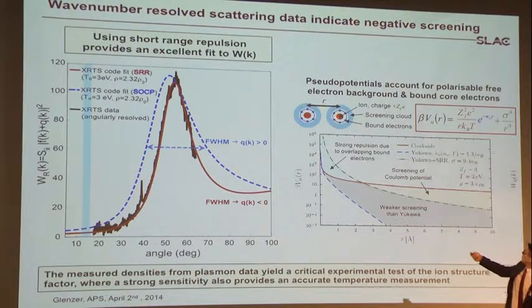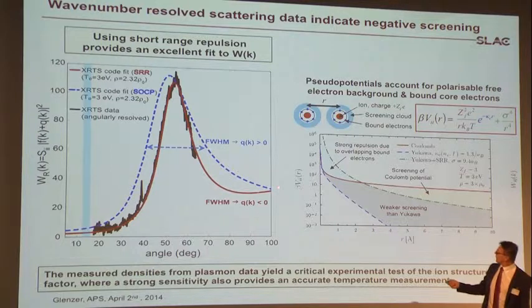So now what happens is, as you compress material, the ions get closer and closer. This is aluminum, so you still have bound electron states. And what the bound electrons are doing, they're still orthogonal to everything else, so all the other wave functions in the system. That means they're actually weakening the screening cloud around the ions. Sometimes people call this negative screening, but one can think of this as a short-range repulsion. And now you get this green potential here, which is a Yukawa potential that includes short-range repulsion. And as we include this, you get the red theoretical curve, which goes right through the data.